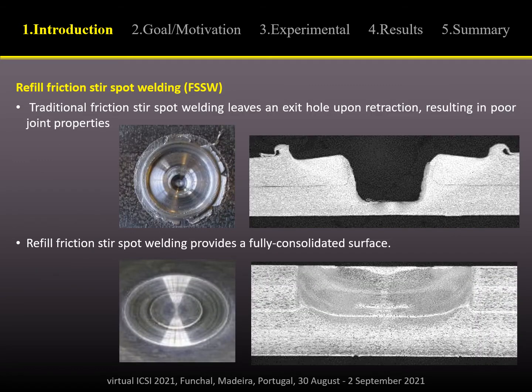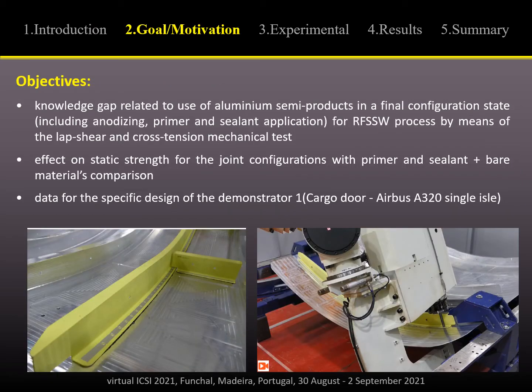Refill friction stir spot welding is one of the promising methods, consisting in joint creation by plunging and retracting the rotating tool into the overlapped sheets. The main advantage of this method is that the process doesn't leave an exit hole after welding, like here, and is able to provide a larger area weld, resulting in improved weld strength. The principle of this welding method will be shown in a video presented later on.